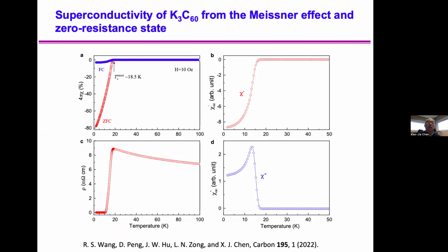Here I show the example we published 3 years ago for the potassium-doped carbon 60. That's ZFC from DC measurement. The real part of susceptibility and the imaginary part of susceptibility clearly show the peak. Also resistivity, that's from the same samples. That's the first time in history carbon 60 showed two characters supporting superconductivity.